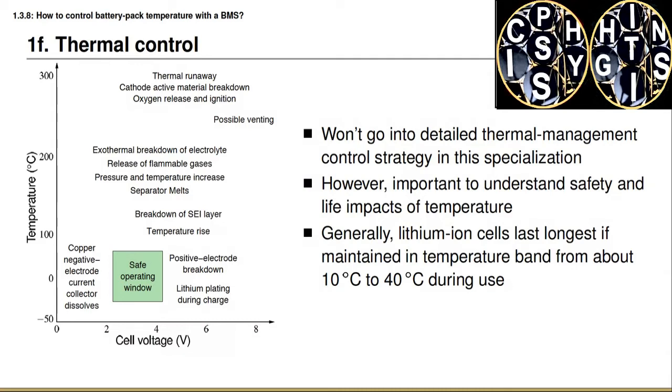These primary causes can also lead to secondary effects. For example, overcharging can cause temperature rise, which causes the solid electrolyte interface (SEI) layer — a film that grows on the negative electrode particles to passivate them — to break down, exposing fresh graphite to the electrolyte solvent, causing more SEI to grow. This reduces cyclable lithium and decreases battery capacity. The very act of SEI formation and growth can itself cause temperature rise, so temperature rise causes SEI growth, which causes more temperature rise — a compounding problem.